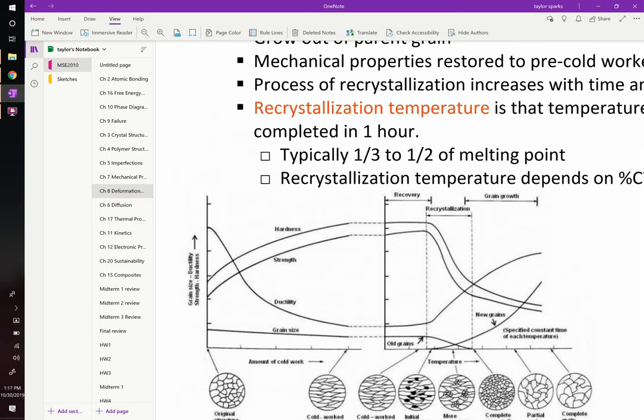Yeah, and think about our rule of thumb from this chapter: if you made it harder for a dislocation to move through the material, you made it stronger. So if you've got a bunch of grain boundaries, imagine like a student is trying to scooch his way across the room, right? Well, when he gets to this part, you can't scooch as easily because it's awkward. He has to change directions. There's like this gap. This is probably filled with a jumble of misplaced atoms. So it acts as a barrier to dislocations. So the smaller your grain size, the more of these boundaries you have that mess up your dislocation motion. So not surprising that as the grains grow in this region, it's just getting weaker and weaker, softer and softer, because there's bigger regions that the dislocations can slide through, slip through.